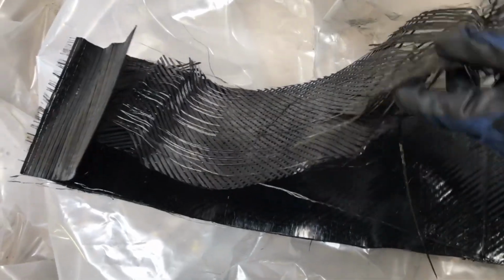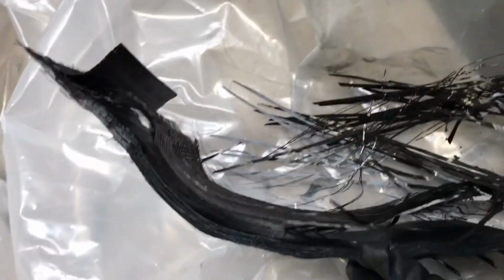I think the biggest challenge with the wind blades was all the inert materials present in a wind blade. You can think of the glass fibers and everything that is not easily broken down, because inert materials do not convert into chemicals. We only performed the combustion, so we received black colored samples, and we expected that there was only glass fiber in it, but in the end it looked like some of the fibers didn't turn white, so it was carbon. So the biggest lesson learned: material passport. We have to know exactly what type of material is in it before we use it as feedstock for our furnace processes.